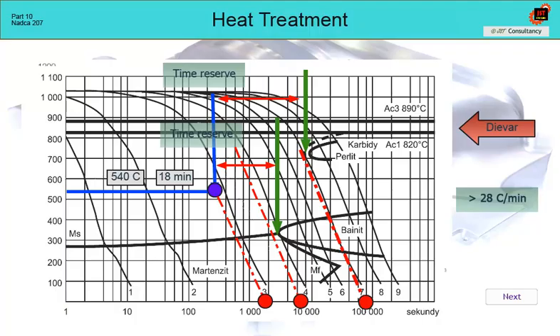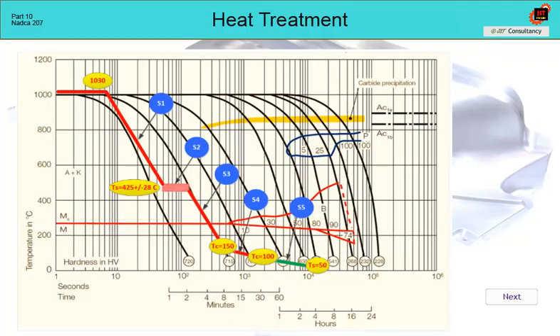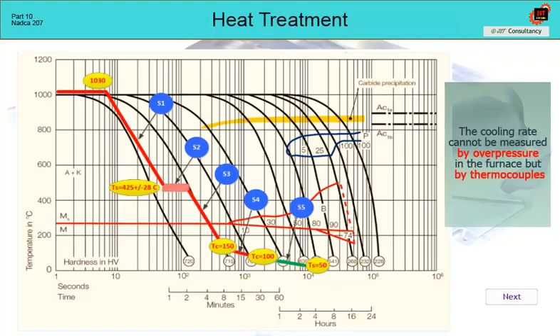In order for all this to work well in practice, the final program for quenching die casting dies, if placed directly in the CCT diagram, must look like this. But we must keep in mind that the cooling rate is not specified by the gas overpressure in the furnace, but only and exclusively by the measurement from the batch thermocouples. This is crucial for the proper management of the process.